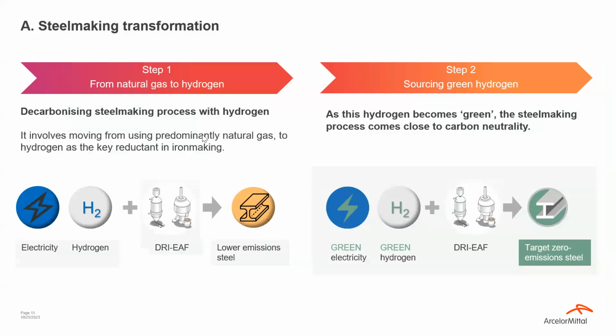Here, steelmaking transformation. The first pillar, as I told you, is that we will transition from blast furnace to DRI. Today, DRI is working with natural gas. The first step seems simple said like this, but it's actually quite complex. We need to switch from natural gas to hydrogen. It means that we need to make our installations technically operational, working with hydrogen instead of natural gas. At the moment, most of the hydrogen comes from petrochemistry, and we usually label this hydrogen as gray hydrogen, which makes it not really a sustainable alternative.